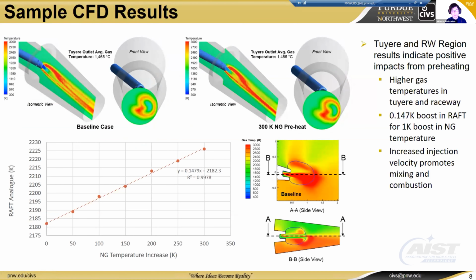Here we have some sample CFD results from the tuyere modeling. This deals with a single variable, in this case, the natural gas temperature. And you can see that we do gain positive impacts from preheating. This results in higher gas temperatures in the tuyere and raceway, about a 0.147 Kelvin boost in raft and a 1 Kelvin boost in natural gas temperatures. Heating the natural gas results in an increased velocity, which promotes better mixing and combustion.